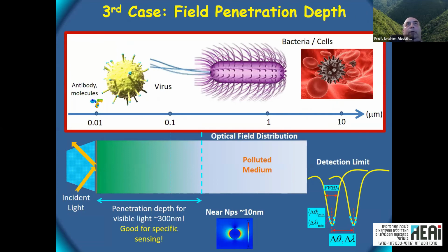Before we move to something else, like the localized plasmons, we will talk about improving or controlling the penetration depth. As mentioned, with a small penetration depth, we can measure up till viruses, which are like tens of nanometers. But if you want cells, we need larger penetration depth.